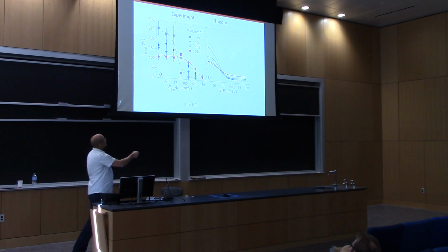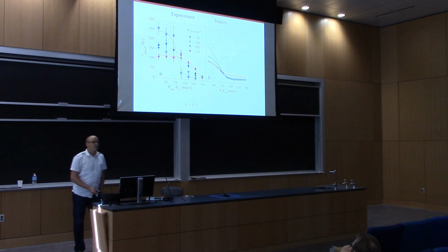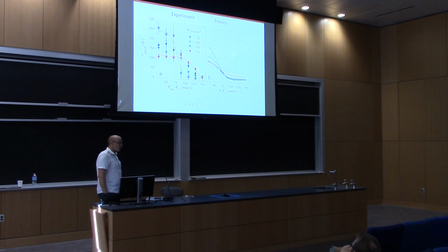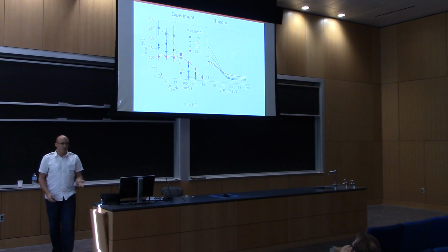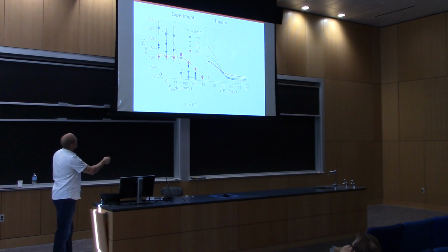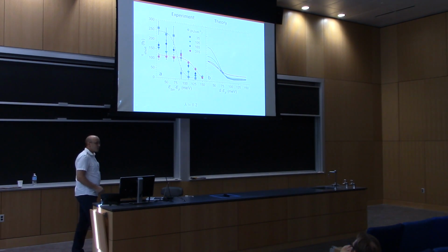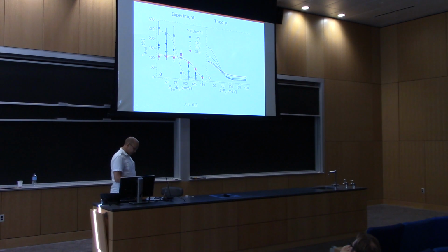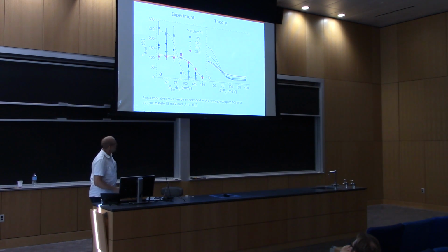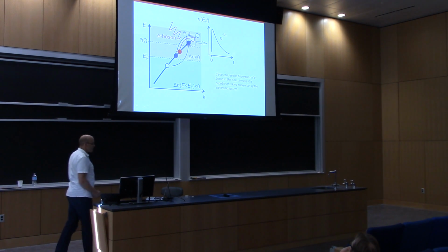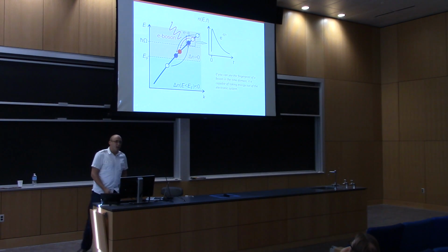Now, one important thing is that the only thing I have in this theory is electron-phonon scattering. That's it. There's no electron-electron. And yet in this material, which is cuprates, where electron-electron is pretty important, we managed to capture a very good portion of the dynamics entirely with just the phonons, which are, after all, responsible for taking the energy out. Okay. So the take-home message from there is, if you can see some kind of fingerprint of a boson, it's probably taking energy out of your system.